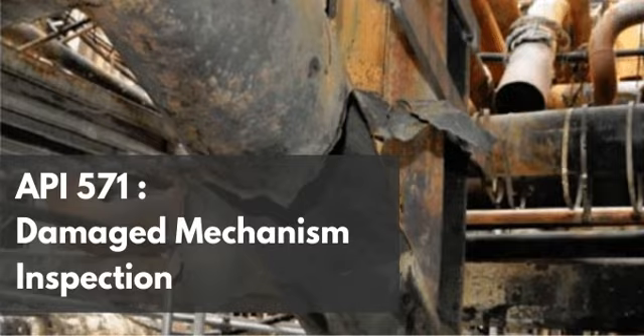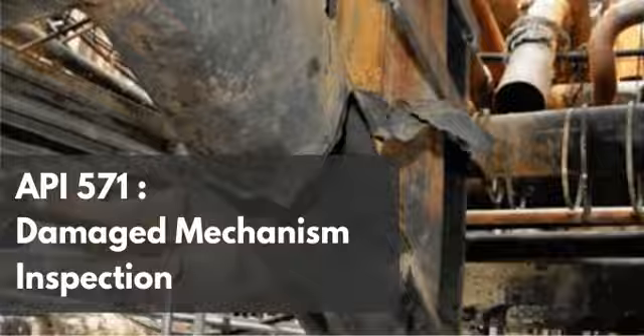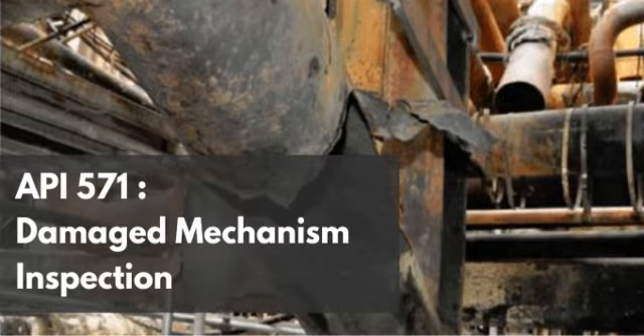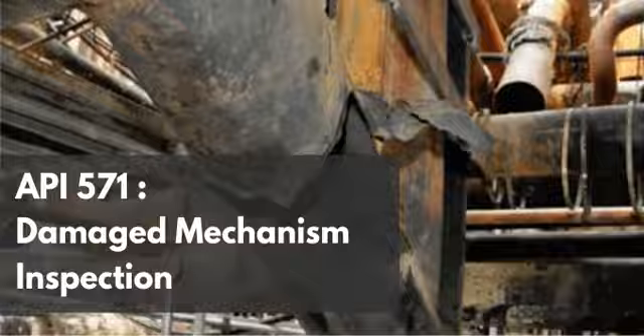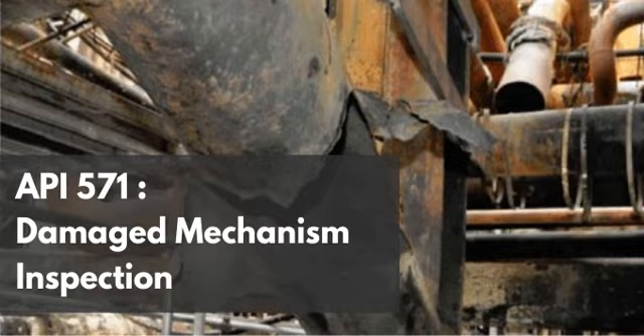Walk us through it. Imagine the exact moment a perfectly clean, brand new, bare steel tube is exposed to this high heat, high carbon gas. The concentration gradient is massive. Because it's all carbon on the outside and none on the inside. Right. You have 100% carbon activity on the outside pushing against the metal and 0% carbon inside the fresh steel matrix. And nature abhors a vacuum, so the carbon rushes into the surface layer of the metal incredibly fast. Like the dry sponge soaking up the water as fast as it can.